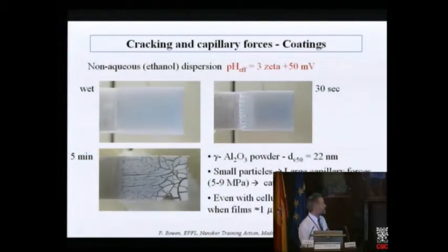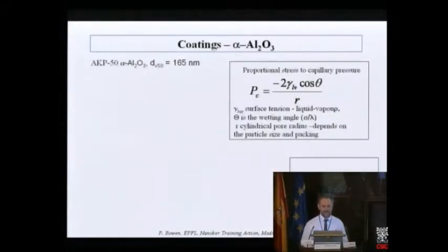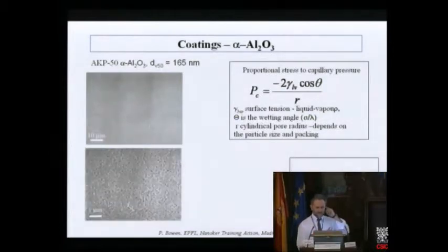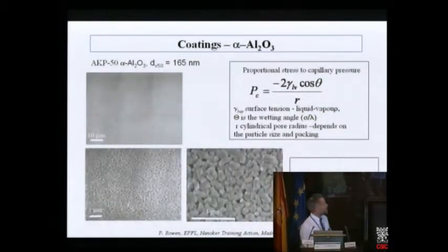The only way we can do it is to have very thin films. If we have 1 micron thick films, then the critical film thickness is not passed. We can create crack-free films, but this is limited. If we look at bigger particles, at 165 nanometers, like the AKP50 I showed you in the first example, we can see that in this particular case, we're okay. We have big areas, no cracks, no problem.